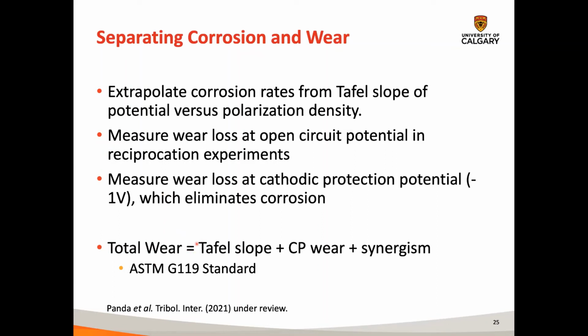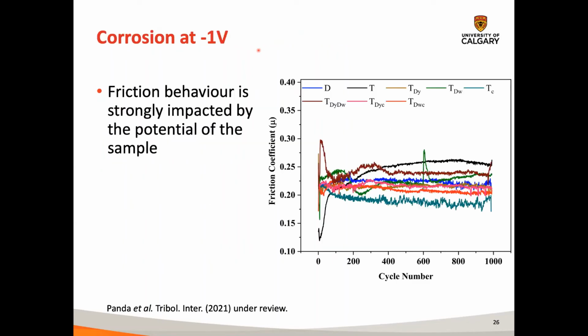And then we make a combination of the total wear equaling the Tafel slope from only corrosion, the cathodic protection potential, which only looks at mechanical wear, and then the remainder between the total wear and these two parameters is the synergism, or the interaction of corrosion and wear to accelerate the wearing out of the pipeline steels.